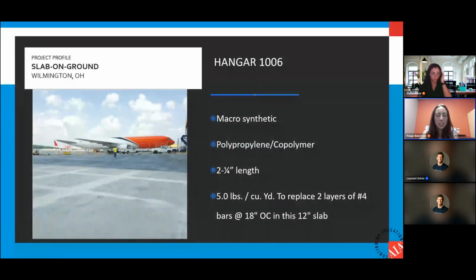All right, so for this hangar project, I like showing this example because, as it was mentioned, macrosynthetics can be used to replace a light duty bar at higher spacing. With this being number 4 bars at 18-inch spacing in a 1-foot thick slab, that just made for a really good option for a macrosynthetic. This was originally spec'd in with 2 layers of number 4 bar. Ultimately, this made for an easier placement for the contractor, saved the owner money when it came to material cost and man hours, since they didn't have to tie 2 layers of number 4s. Some of those benefits would probably be consistent across a lot of these project examples that we're seeing.